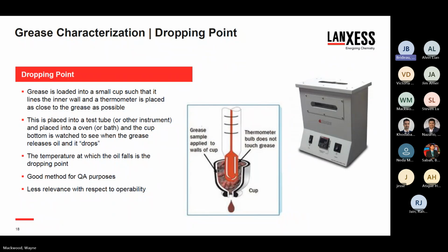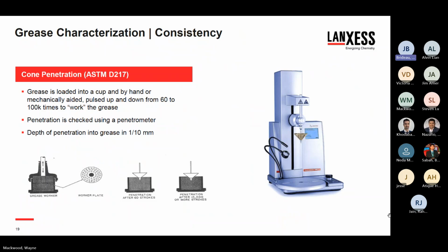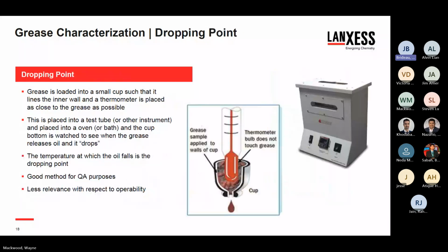And again, that can be affected by the thickener type. That's probably one of the biggest effects, but it can be affected by the oil used, the viscosity of the oil used, the NLGI grade. All of these things, and even additives, can affect that point at which the matrix of the grease wants to release that oil, and the temperature. So there's a lot of ways that can be boosted or negatively impacted. It is a decent quality assurance test, but as I'll discuss in a bit, it's really become not a test to characterize one grease versus another or to tell whether a grease will operate at higher or lower temperatures. It's less value than that, more value in a QA test.